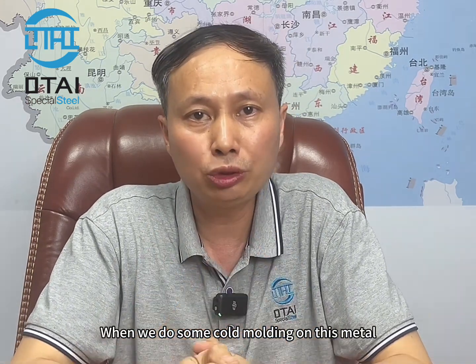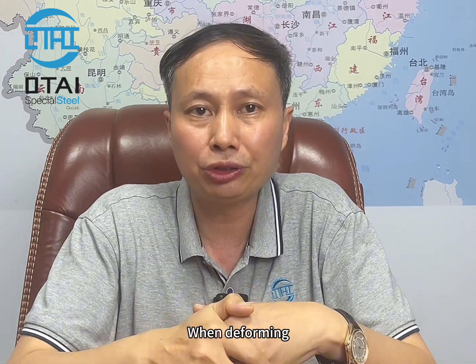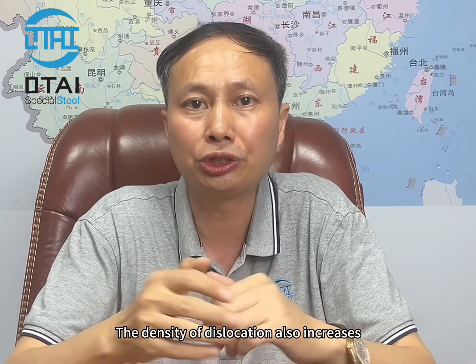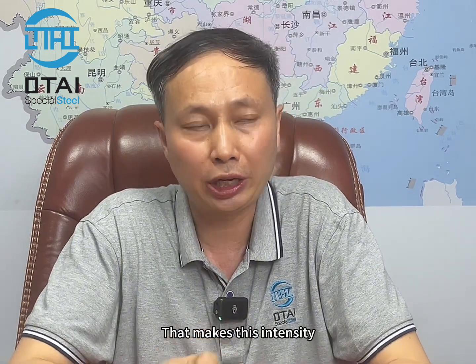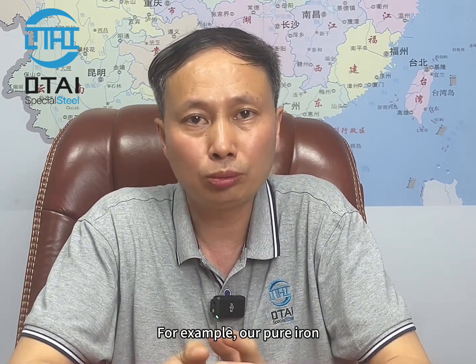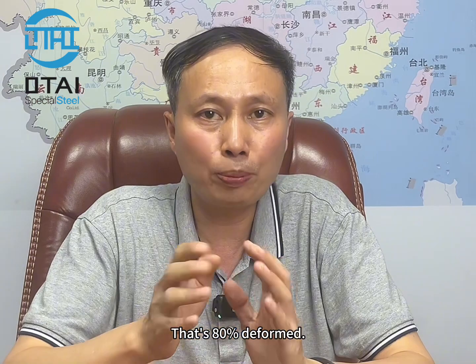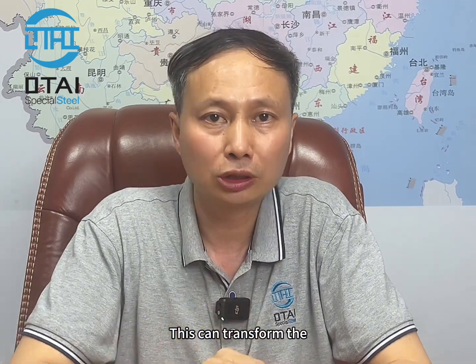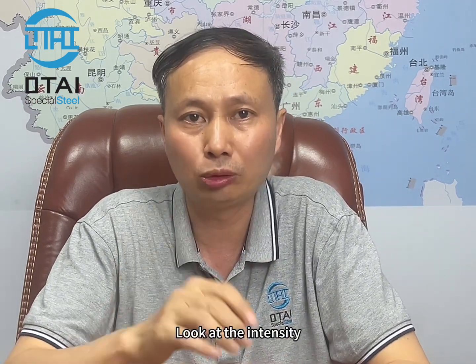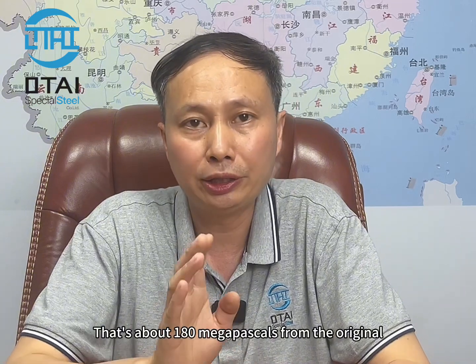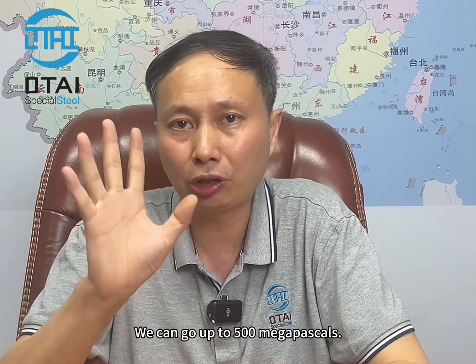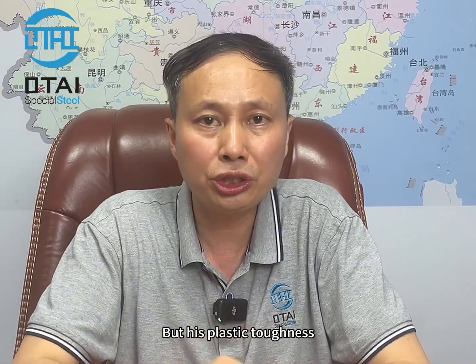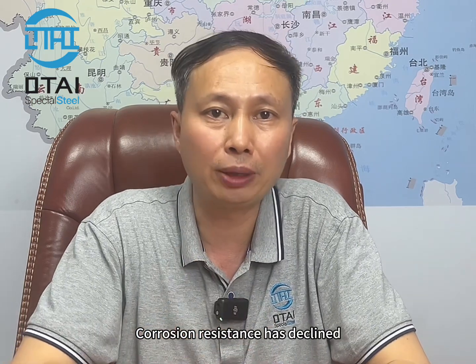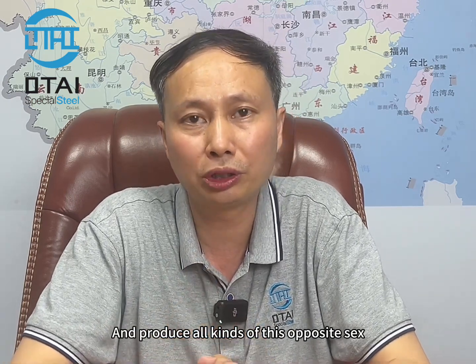When we do some cold forming on this metal, when deforming, we refine this grain and elongate it. The density of dislocation also increases. That makes the strength and hardness increase. For example, pure iron that is 80% deformed: look at the strength, it goes from about 180 megapascals originally up to 500 megapascals. But its plastic toughness and corrosion resistance have declined, producing all kinds of anisotropy.